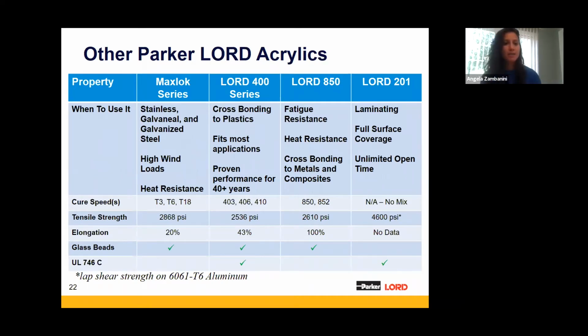So the first one is Maxlok. Maxlok is our superior heat resistance, environmental resistance, and strength adhesive available today. It works really, really well on stainless, galvanneal, and galvanized steel. And again, it's really because of its higher peel resistance. So that's another feature of the Maxlok. Because of that, we do recommend it for higher wind load applications. And we offer it in 3 different cure speeds, which make it really great for fitting your ideal process time.